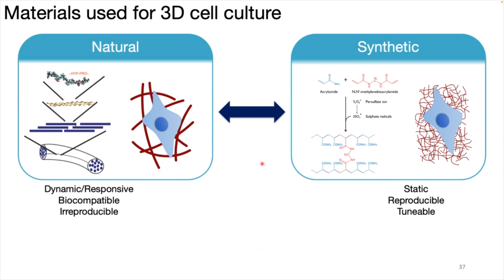very porous structure. On the other hand, you have the synthetic materials, and those are typically chemically cross-linked polymer materials. Polyethylene glycol is used a lot. Polyacrylamide hydrogels are also used. So you have your monomer, and then you induce the polymerization, and you have your material. But as a consequence, there is no hierarchy, everything is the same, and your pores are much smaller, and your fibers are just basically a monomer molecule, so they are not very thick.